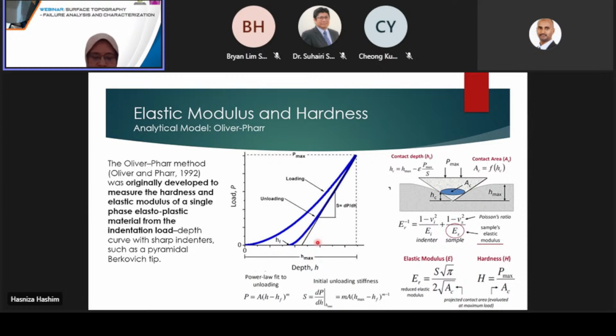So first, we need to calculate the stiffness of the material. The stiffness is simply the slope fit of the unloading curve at max load. So from this equation, the contact depth is then calculated as follows.